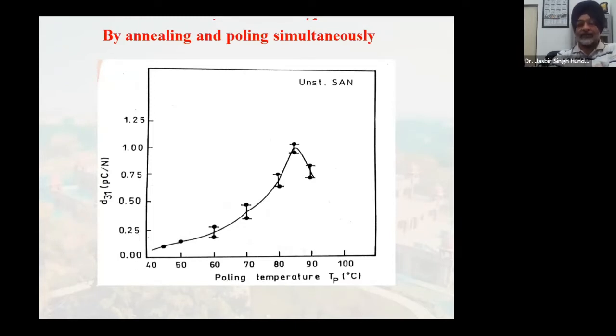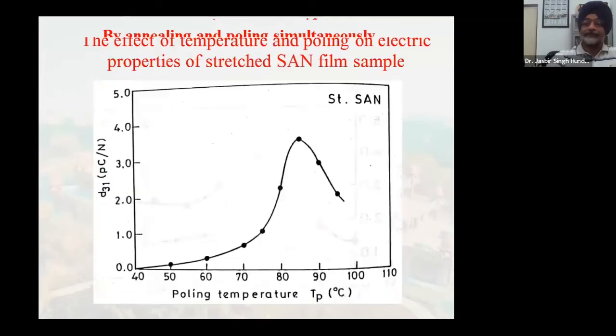Higher the poling temperature, more would be the mobility of the dipoles. There would be better chances of the dipoles getting oriented in the field direction. And that's why with the increase in poling temperature, D31 improves, because ultimately it is directly linked with the polarization. But when the poling temperature is increased too high, then again dielectric breakdown starts, thereby reducing D31. So 85 degrees centigrade was found to be the best poling temperature for styrene acrylonitrile, right?